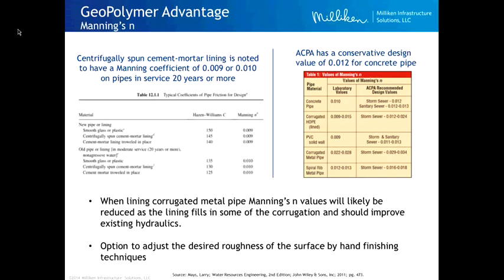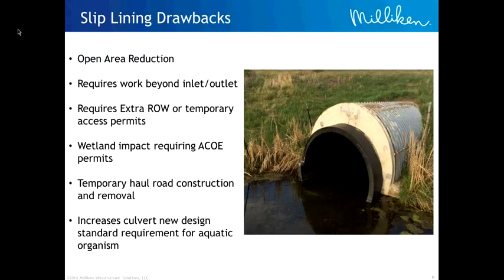So if you felt that surface, it's a little rougher than smooth concrete that comes out of a pipe form. So we think it falls within a range of 0.012 to 0.015. We have done projects where we could not increase the Manning's n in sanitary sewers, and so we will go in and spray it and then come back through and hand trowel that to make it smooth. So if that's critical, we can do that. Any questions on that?